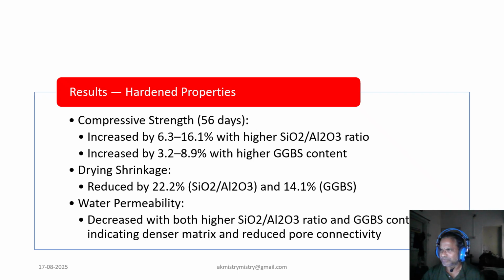Compressive strength improved with both higher silica-alumina ratio and increased GGBS content. So this is a very important finding. The 56-day strength grew by up to 16.1% with increased silicate and up to 8.9% with slag addition. Drying shrinkage was reduced by 22% and 14% respectively, while water permeability also decreased, indicating a denser, less porous microstructure.